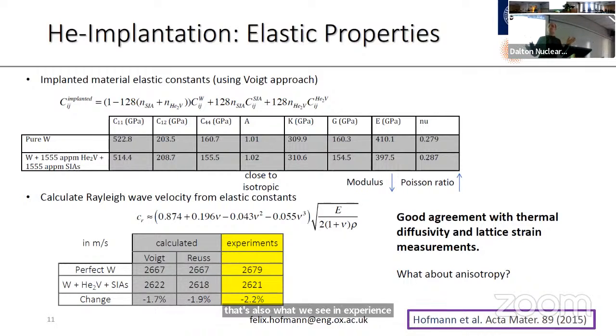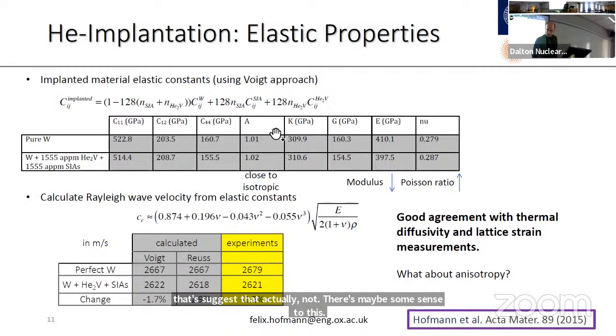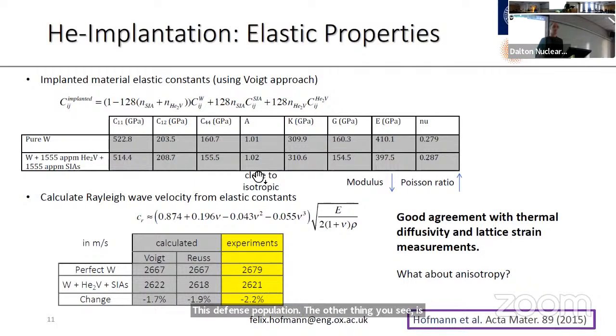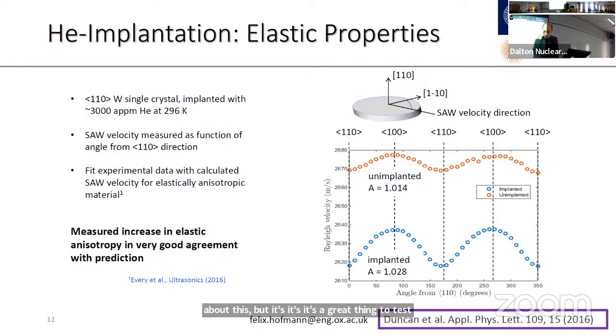So that suggests that actually there's maybe some sense to this defect population. The other thing you see is that there's this change in the elastic anisotropy. So our materials become very slightly more elastically anisotropic. Note, of course, from an engineering perspective, you don't care about this, but it's a great thing to test whether our model is actually correct, right? So rather than just measuring surface acoustic wave velocity in one particular direction, if we look at a single crystalline sample, we have the ability to look at the propagation of surface acoustic waves in different directions, and thereby we're sensitive to the elastic constants.